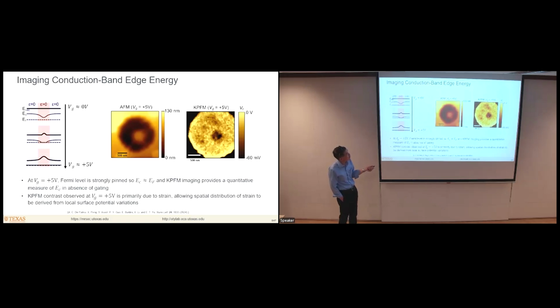And that's shown over here, right? So this is the Kelvin probe measurement of the surface potential at a large positive gate bias voltage. And what you see here is that, in fact, we do see this region corresponding to this mesa over here where there is localized tensile strain, and this is essentially a map of the lowering of the conduction band edge energy due to that strain, all right?